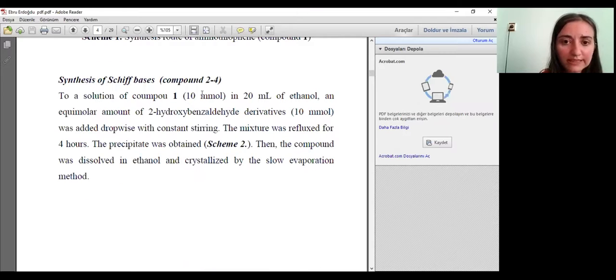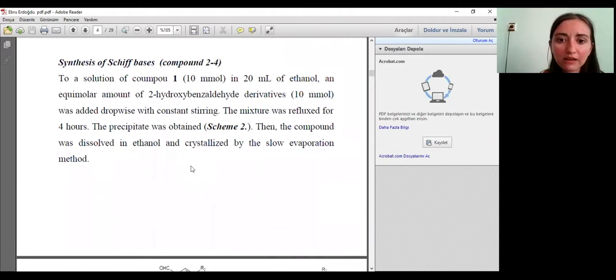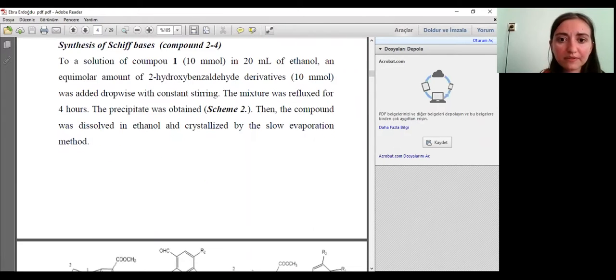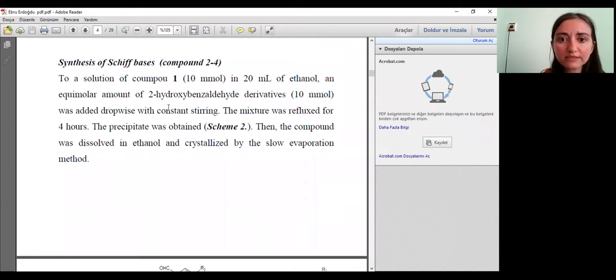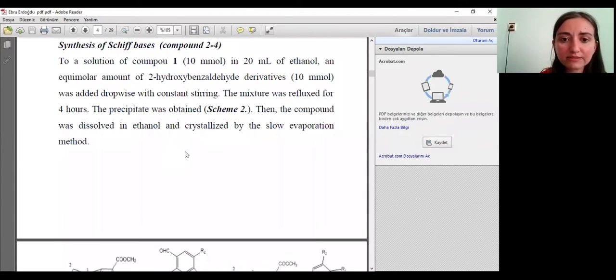For compound 2 and the other ones, the amine was dissolved in ethanol and the aldehyde was added dropwise with constant stirring. The mixture was refluxed and dissolved in ethanol and crystallized.